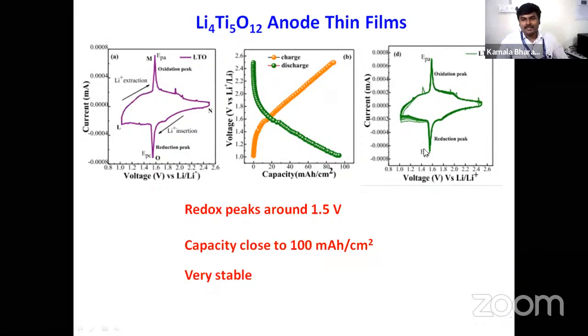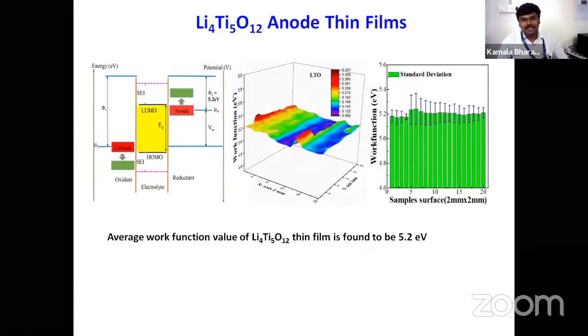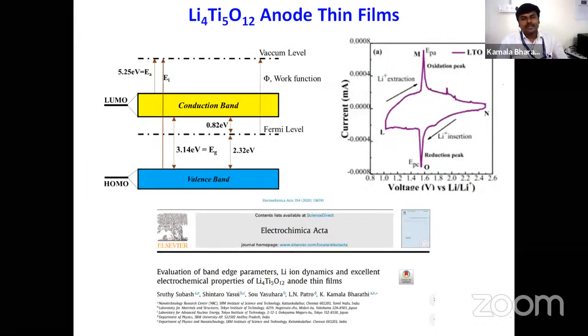And this is the CV curve measured at 10 cycles. You can see that the data can be traced one over another. That means it's a very highly stable material, which exhibits a capacity close to 100 milliampere hour per centimeter square. Again, we measured the work function of this thin film, which is found to be around 5.2 electron volt. In addition to that, from this CV data, we can extract various band edge parameters, which I'm not going to discuss today. So if you go to this paper, you can find how to extract various band edge parameters using the electrochemical CV curve.